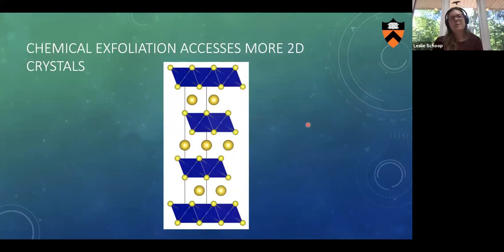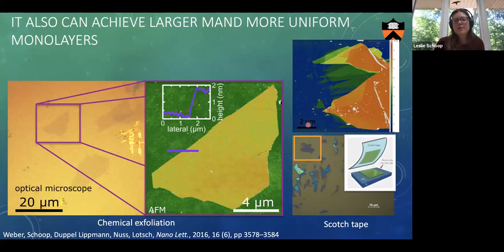Another advantage, for some materials, not all of them, is that sometimes chemical exfoliation actually gets you better and nicer sheets. There are some materials like graphite that you can exfoliate beautifully with scotch tape, and it's not clear how much you can do with chemical exfoliation there. But here's an example of ruthenium trichloride, which is a very interesting quantum magnetic material. I think Puan Ong will talk about this later in the school. If you apply scotch tape to this, it's very difficult to get uniform large sheets. Of course, it's probably not impossible, but there are so far very few papers, if any, on monolayer ruthenium trichloride. But if you use chemical exfoliation, you can get suspensions with very uniform and pretty decently sized sheets. You see the scale bar here, it's nearly 20 microns across.